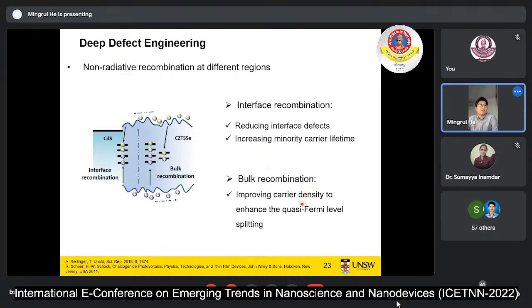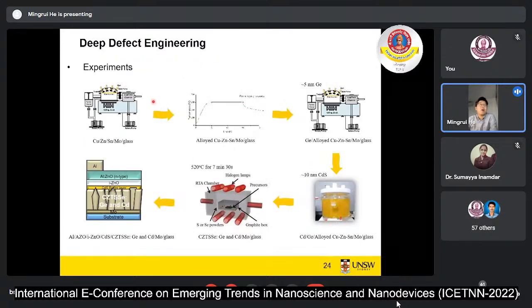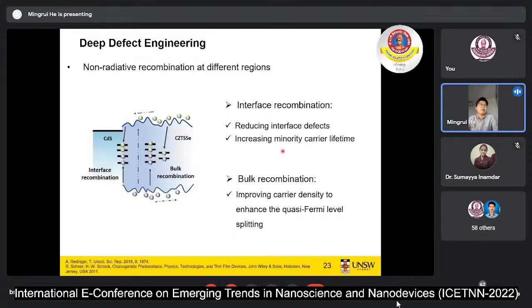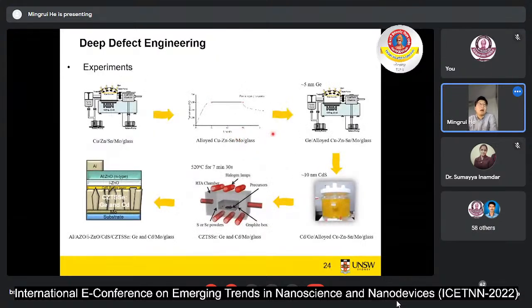Here I would like to mention how I did this doping and alloying experiment. In this experiment, I did cadmium alloying and germanium doping. First, I made the copper zinc tin precursor by sputter. After that, I pre-treated this precursor by a pre-alloying process.